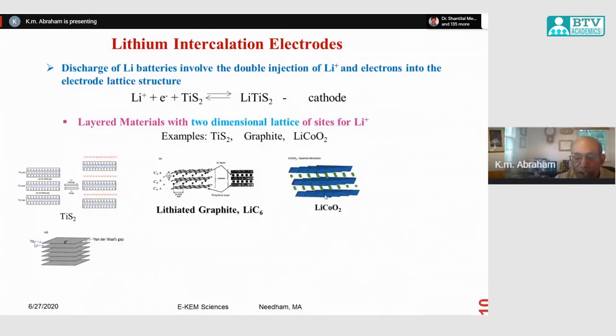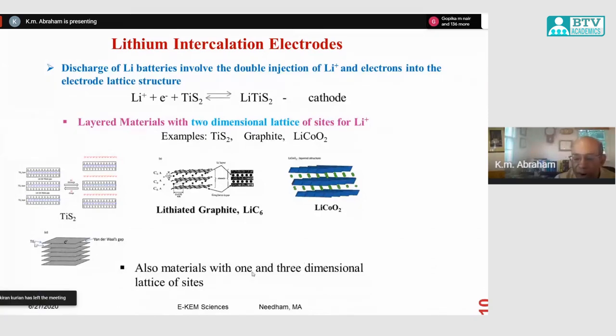Another material is an oxide, lithium cobalt oxide. It has the same kind of layered structure. We have here CoO6 octahedra. They are connected to each other through the faces and corners of the octahedra, and those layers are then arranged one on top of each other. You see, in this case, it's a 2-dimensional lattice. There are also materials with 1 and 3-dimensional lattice of sites.